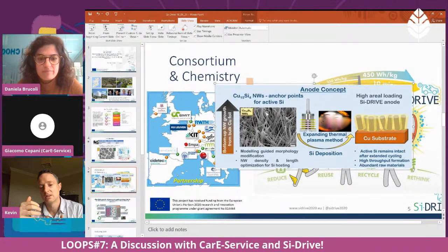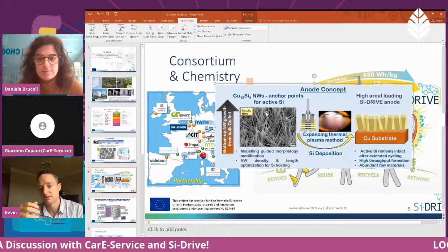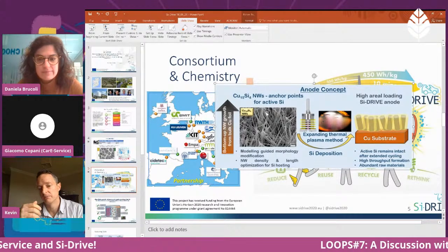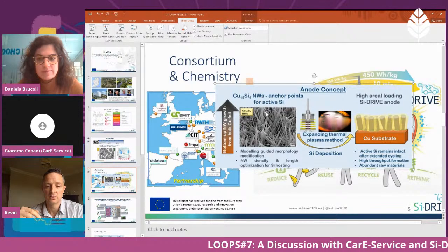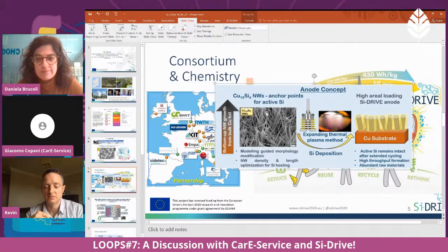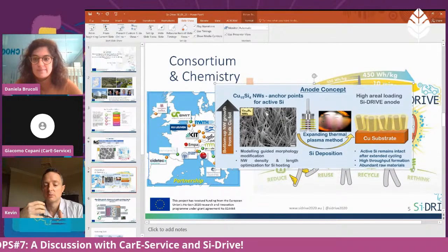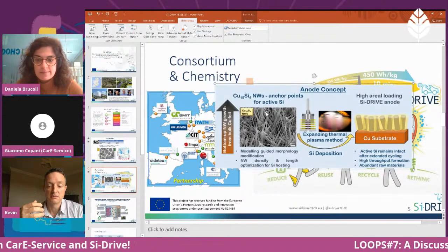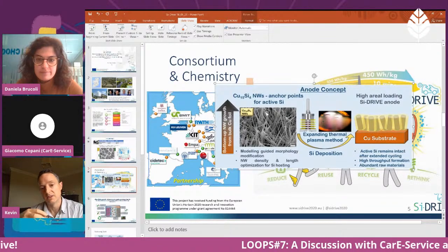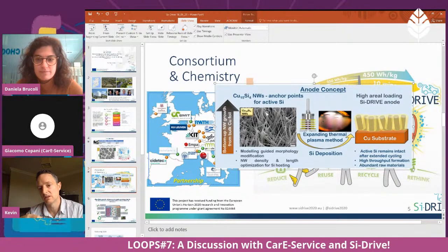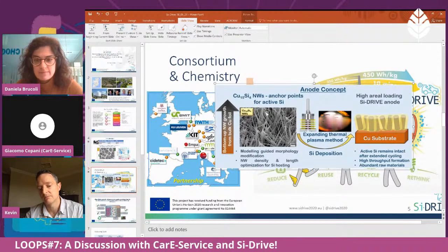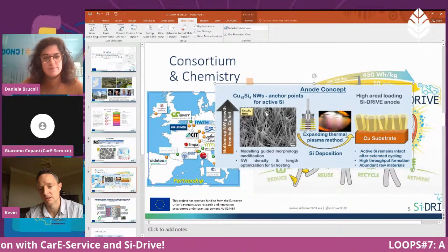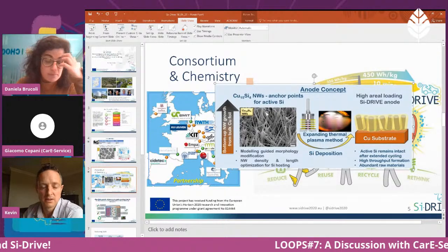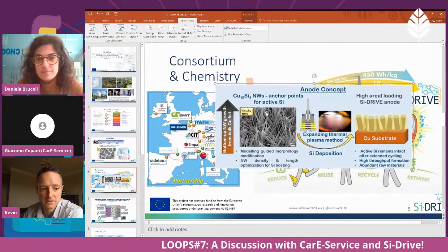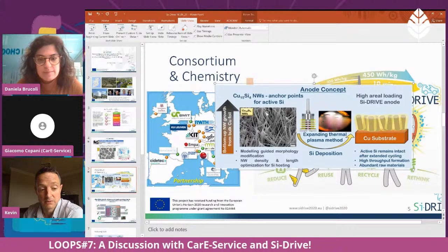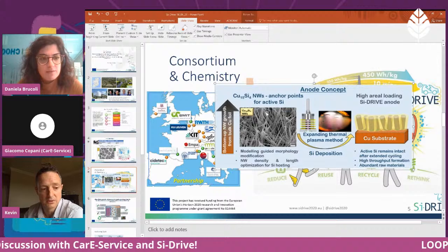And because we can control the amount of silicon that's deposited onto these copper silicide nanostructures, we can get a high area loading. But more importantly, because these copper silicide nanowires don't cycle lithium themselves, they act as conductive pathways. So because of this, we're addressing the poor conductivity of silicon. And because these are nanostructures with high surface area, we get very, very stable cycling. We've shown over 1,000 cycles with this material, whereas if you took a bulk piece of silicon, you would only get a handful of cycles, or even one or two, because the material shatters.